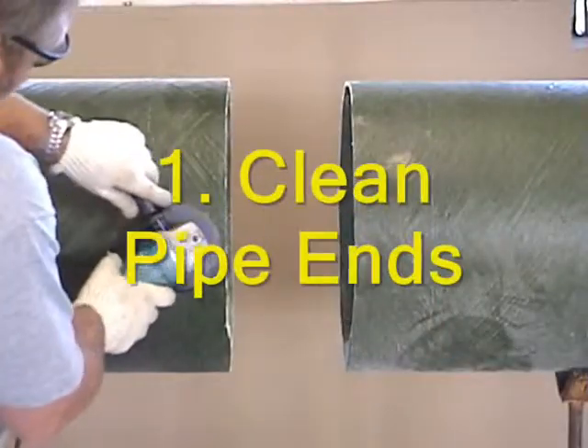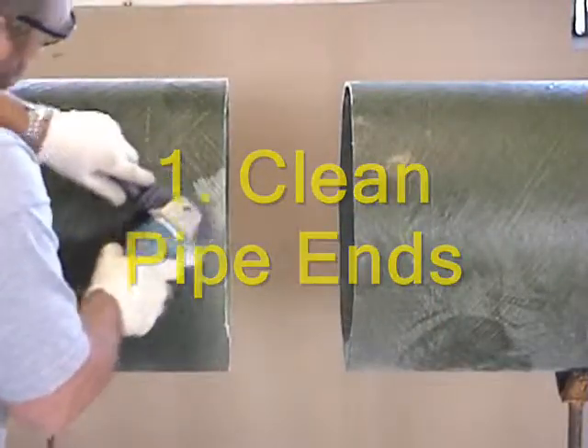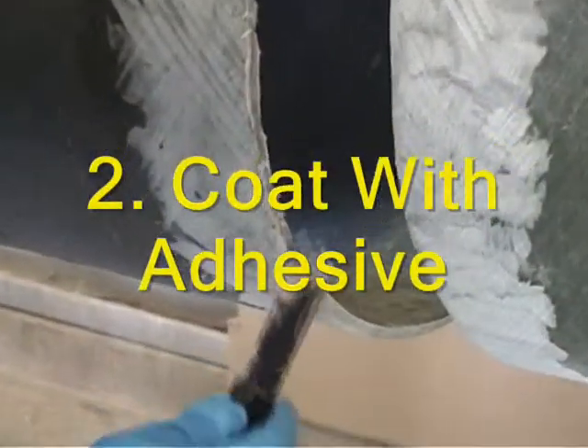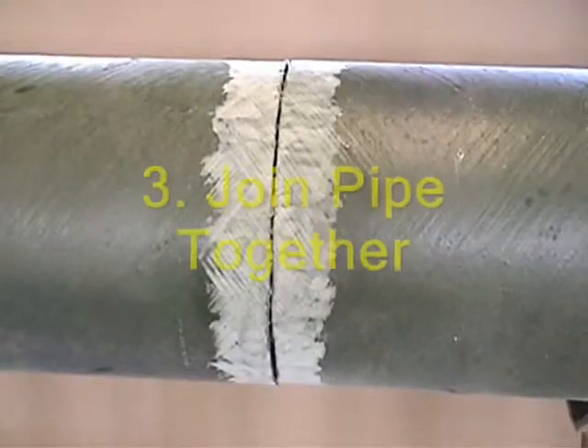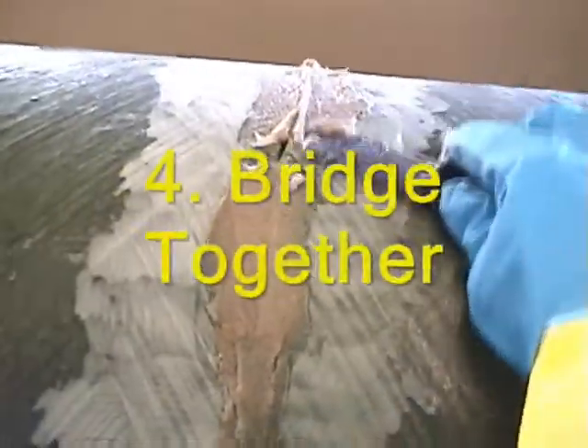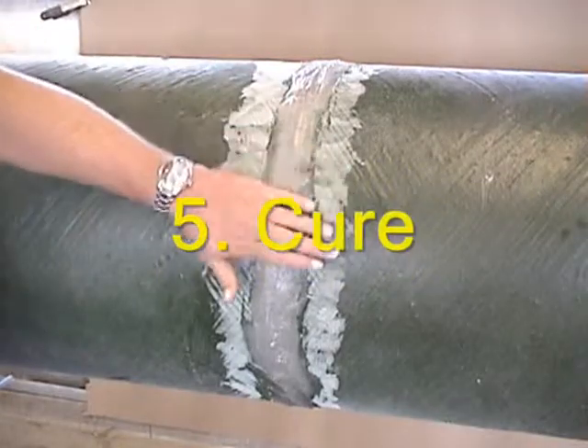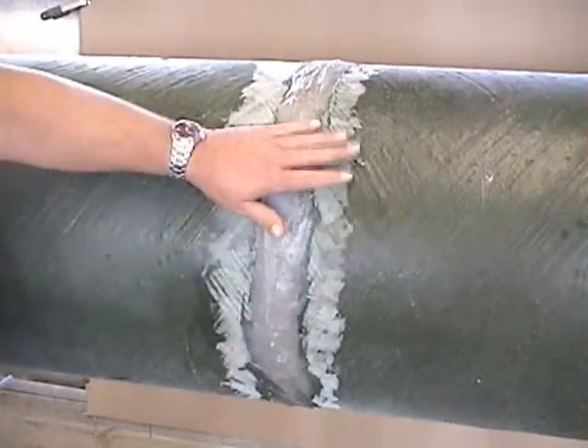We will clean back about 2 inches from the ends of the pipe by knocking off the glaze, taking it down to the dull finish. Then we'll coat the cut ends of the pipe with some of the adhesive supplied in the kit. We'll join the pipe together, then bridge them with the adhesive, and then cure that out so it will hold the pipe together while you're applying the butt wrap.